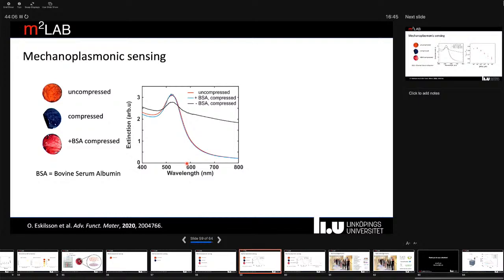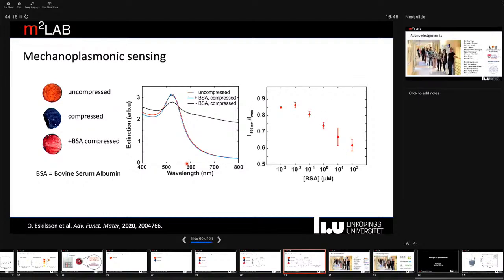So by essentially using mechanical pressure here, we can sense what goes on at the nanoparticle surface. And also reasonably then, the more proteins you have on the surface, the more efficient these proteins are at inhibiting this mechanoplasmonic response. So we can also get a concentration-dependent response.